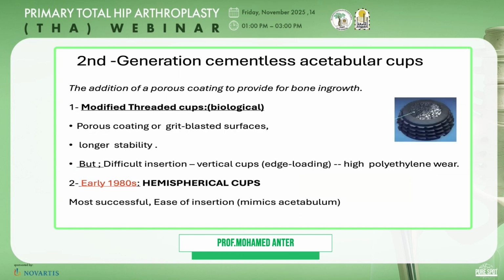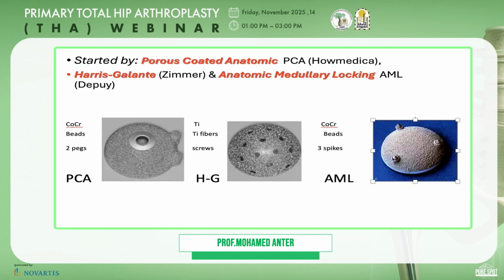For the second generation cementless acetabular cups, we have added the porous coating to provide the bone ingrowth. So we had the modified threaded cup, which had mechanical and biological fixation. It had a longer stability, but also it had difficult insertion. It's always vertical, so there's edge loading and high polyethylene wear. In the early 80s, we had the era of the hemispherical cups, which we are using today. So we have the second generation hemispherical cups like the porous coated anatomic from Howmedica, the Harris Galante from Zimmer, and the anatomic medullary locking from DePuy.